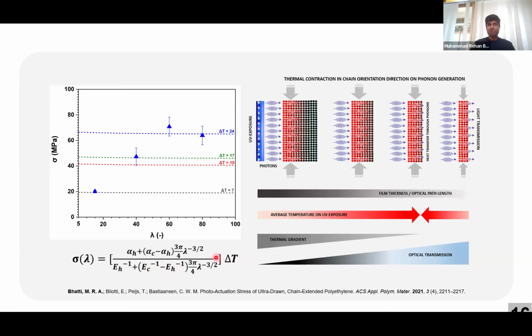But there is a limitation between the polymeric chains. If we exploit the full potential of the polymeric chain, which is somewhere over here, then we will be able to create the highest possible illumination temperature. But there is also a drawback of polyethylene: it cannot bear too much temperature. There is a capacity, otherwise it can start to degrade.